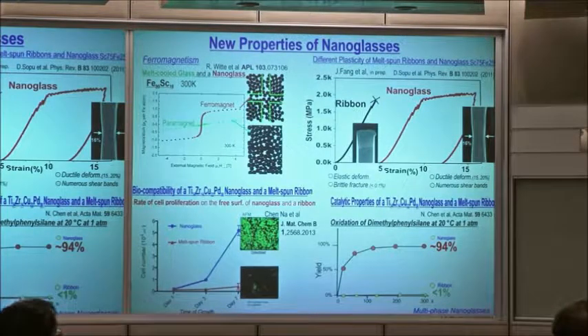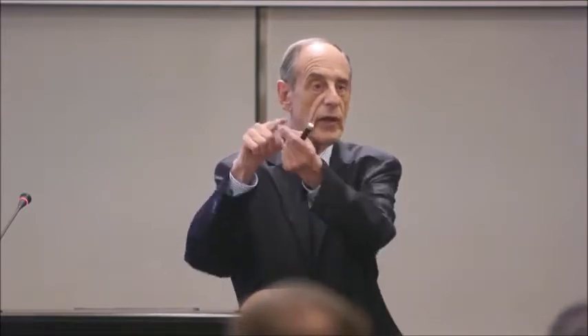The ribbon and the nanoglass, is the thickness the same or different? The thickness was the same. Yeah, and the ribbon fractures, one shear and fracture, and here it just strains and doesn't fracture. And on the computer, what you see is that every interface initiates like a grain boundary, where dislocations come out, and here shear bands come out on the computer. But they cannot run across. They can run to the next interface, and then the next interface nucleates new shear bands. And this is consistent with what we get here.